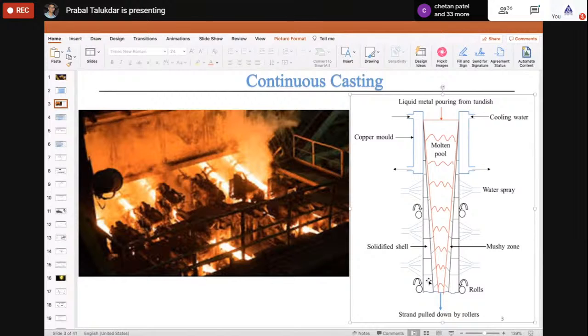Sometimes the billets are not of the size which you want, but take some rhomboidal shape because of the non-uniform heating, right? Because of the high temperature, thermal stresses also evolve in the billets, and because of that, the quality of the steel is not as good as desired. So the problem was that we need to design this copper mold in such a way that the quality of the steel which comes out from this process is good enough. That's the main idea.